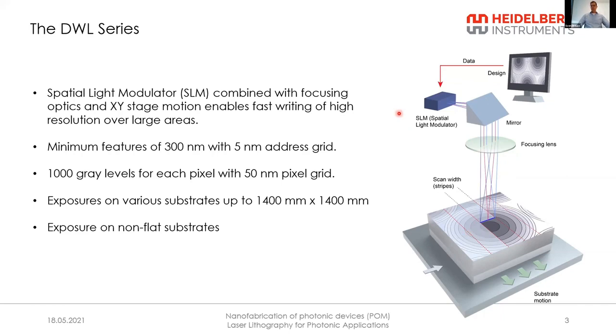The spatial light modulators that we use in the DWL systems have the advantage that they're very fast, and they offer the possibility to modulate the intensity of each pixel with up to 1000 levels. So for grayscale exposures, which is the main application for this tool, it offers very good capabilities. But also the systems offer the highest resolution that we can offer, down to 300 nanometers. And it is possible to expose these high resolution features and also these grayscale features on substrates as big as 1.4 meters. That's the theoretical limit.